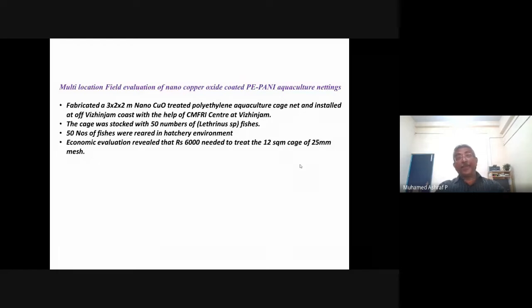Then we prepared a cage with the treated net material and a control, and it is exposed at our sister institute location in Trivandrum. This control is at the CMFRI location at Vizhinjam, and we made a cage, and in that we kept 50 Lethrinus species of fish, and at a similar time we kept 50 in the hatchery also, just to compare.